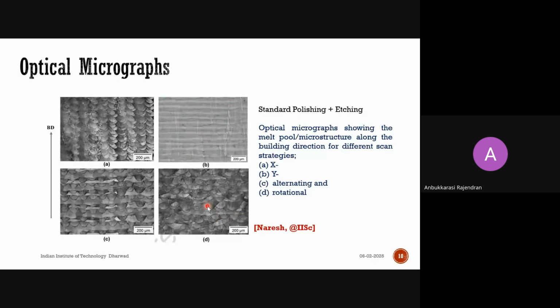So this is basically for properties, as I mentioned, since the internal microstructure is directly related to the properties. To achieve certain properties, the author might have done such variation in the deposition printing. Okay, so after printing, there are deposition layers and internal microstructures. They cut the sample, prepared it with the procedure I mentioned, then used a suitable etchant, and these micrographs were taken under the optical microscope.